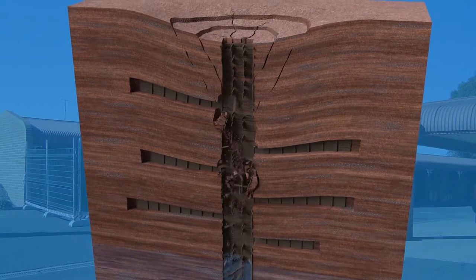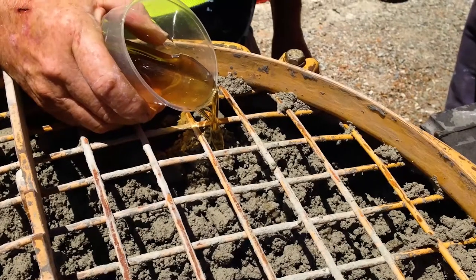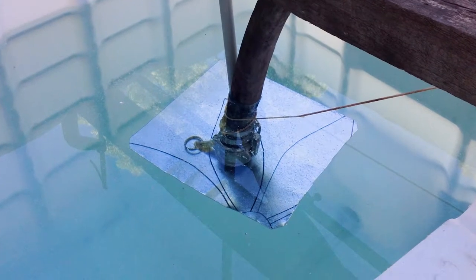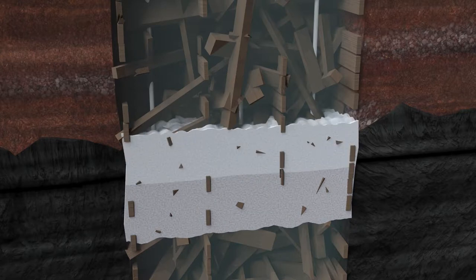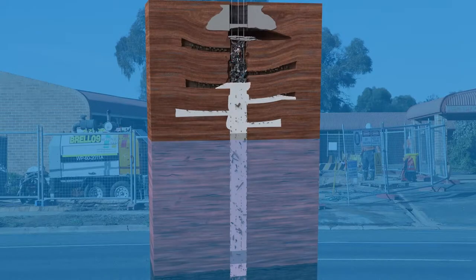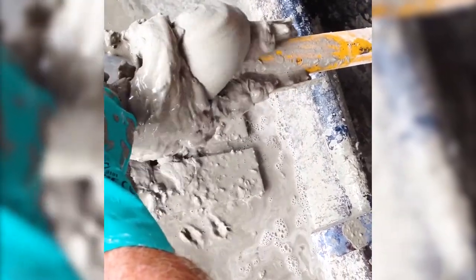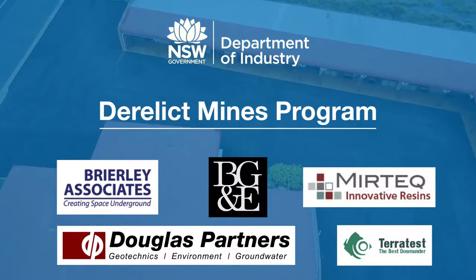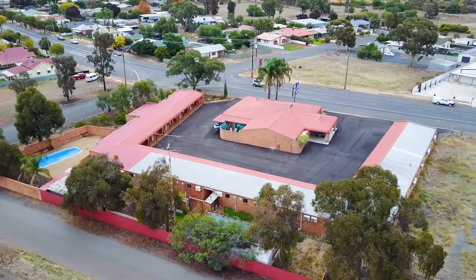Mainmark remediated one of the most technically and physically challenging derelict mineshafts in New South Wales, Australia. Using a bespoke grout formulation and self-releasing grout deflectors, it placed a neutrally buoyant plug 30 metres underwater at 3 bar to support 270 cubic metres of backfill material. The neutrally buoyant, non-dissolvable grout formulation and custom application method was an Australian first and a major achievement for the project. It involved extensive consultation and management of external experts. To Mainmark's knowledge, the solution is unrivalled.